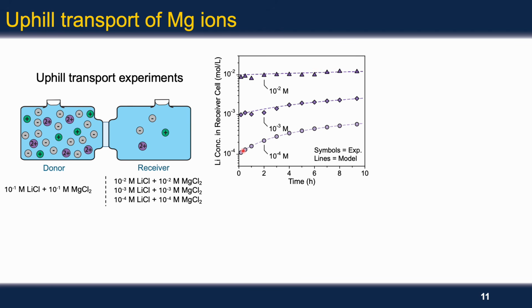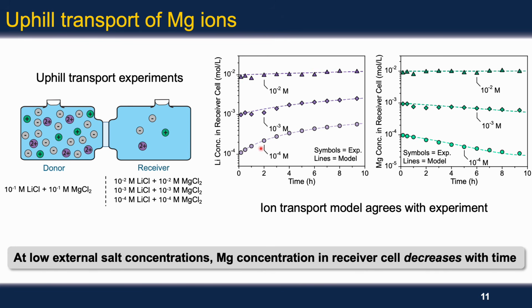However, when we look at the magnesium concentration, we found a decrease in the receiver cell as a function of time, particularly at low total salt concentrations, which implies that there is indeed uphill transport of magnesium ions against their concentration gradient. We also developed an ion transport model based on the Nernst-Planck equation. I won't discuss it in this presentation, but you can read it in the manuscript. This model agrees well with the experimental uphill transport results as shown here.